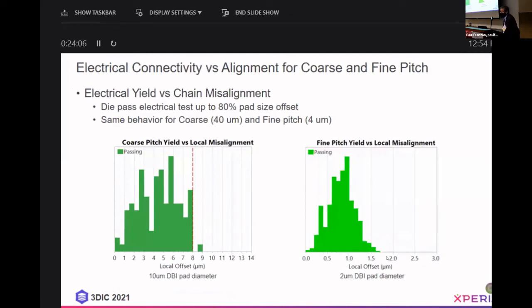This shows a very interesting effect that we've noted on the alignment or misalignment of the chains and how much misalignment we can tolerate. On both the coarse pitch and the fine pitch, we're seeing that an 80% misalignment of the pad size can be tolerated before we start to see a drop off in the connection. So this is data from multiple wafers showing that with these various alignments, which are the results of the variation of the pick and place, everything is connected with the 10 micron pad up to 8 microns of misalignment, and then it just drops off. And with the 2 micron diameter pad, everything seems to be connected up to about 1.6 microns, and then it drops off. So it's interesting that with these two pad sizes, we're seeing roughly the same tolerance percentage-wise for misalignment.